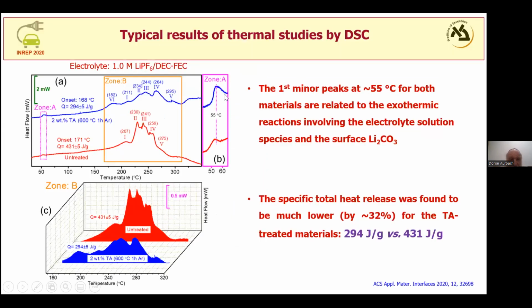And whenever we reach this, we also have a good thermal stability. So here you can see a comparison of heat evolution in DSC, in differential scanning calorimetry, of cathode materials with electrolyte solutions. And you can see the difference. When we have a treated material, the heat evolution is much less compared to untreated material. So it's nice to see the correlation.